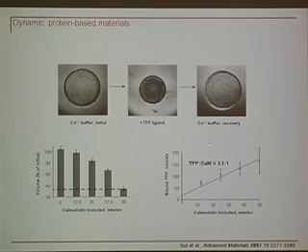The binding stoichiometry is close to what you see in solution for Calmodulin binding to trifluoperazine, which is roughly 4 to 1 in solution, but it's not quite as high. So the suggestion here is that not all of the protein that's incorporated remains able to bind its ligand, but quite a lot of it does.